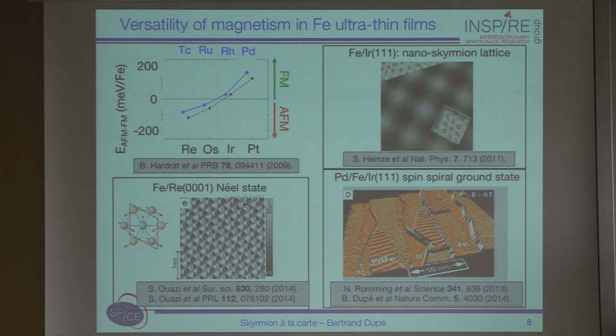And what is very interesting here, in order to have a spin glass, you need to have frustration. What is very interesting is this region here, where the difference of energy between the ferromagnetic and the antiferromagnetic ground states is almost zero. So then you can grasp that there will be a lot of frustration.